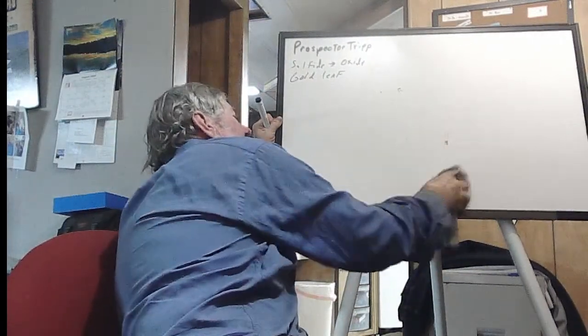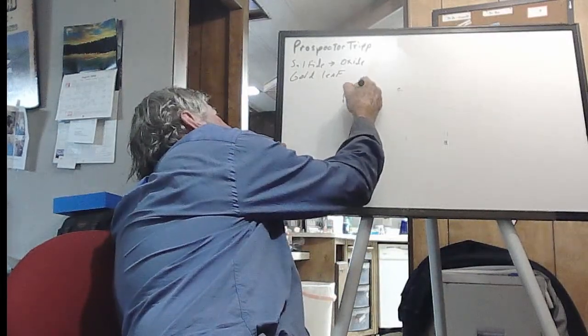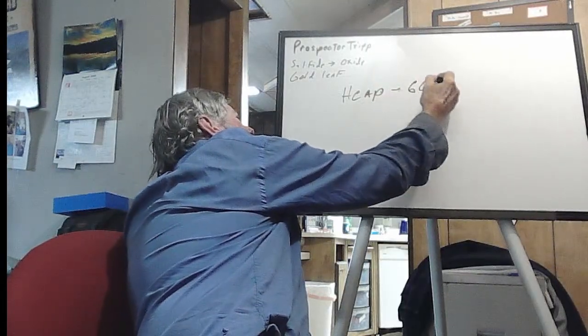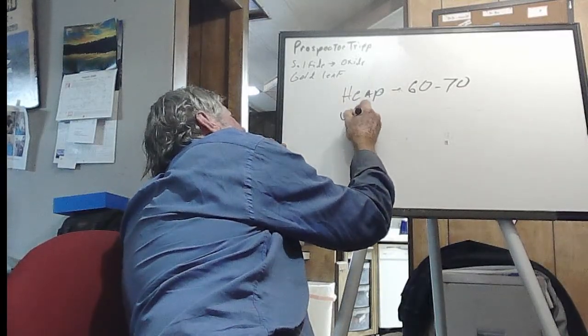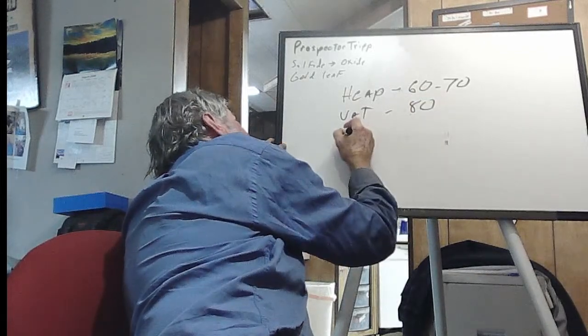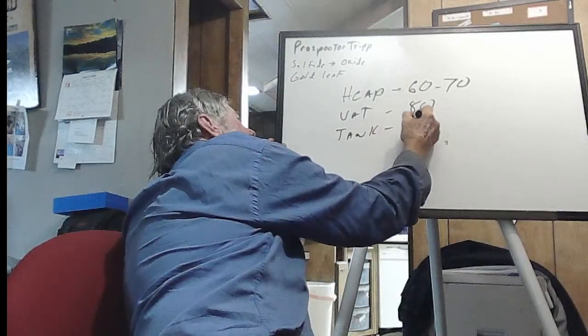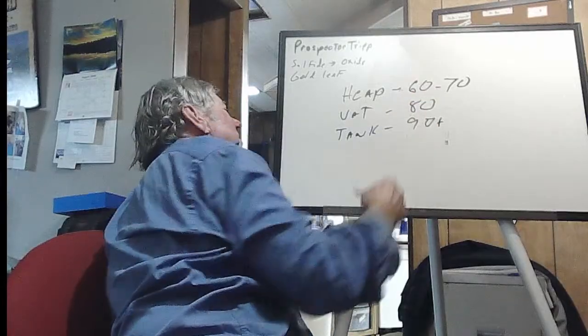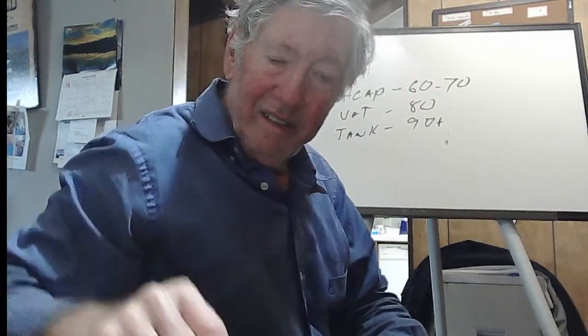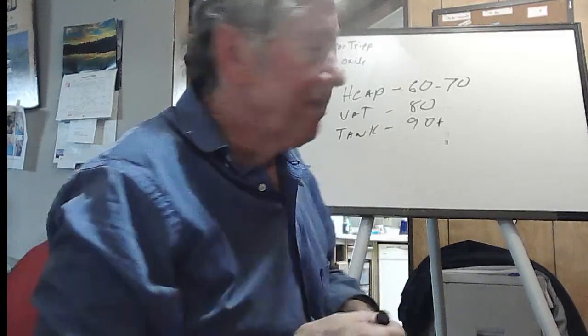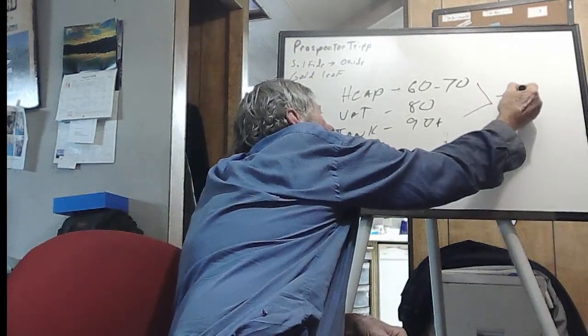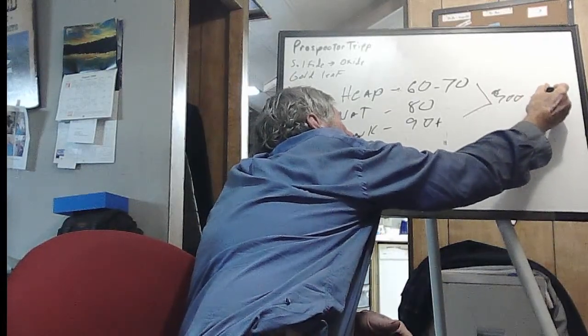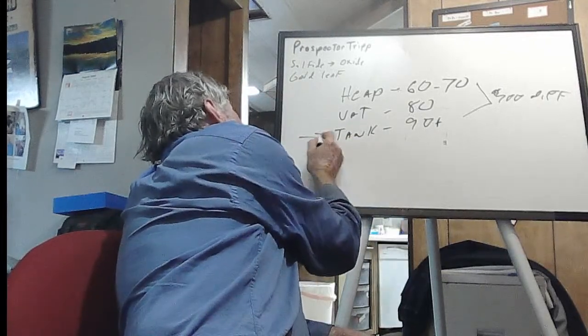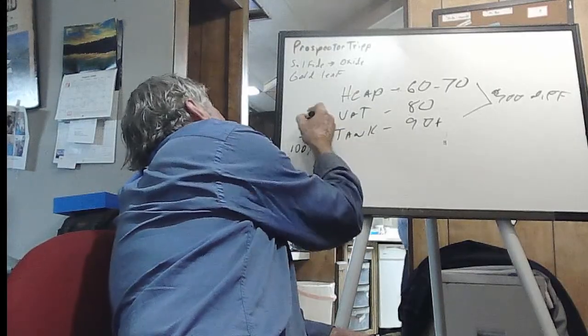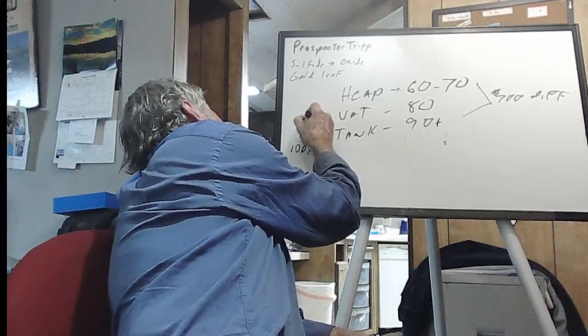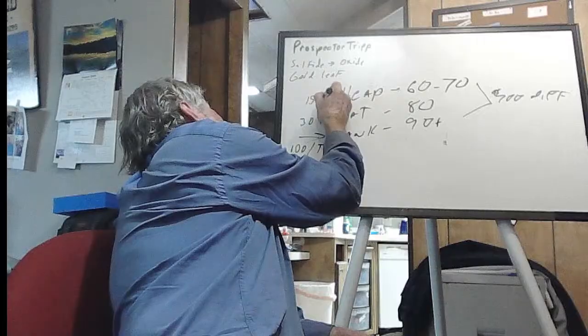For example, heap leaching might be 60 to 70%. Vat leach, call it 80%. Tank leach, agitated tank, 90+%. Okay, so 20% of 1 ounce to the ton would be $700. $700 difference. This cost might be $15 a ton. This would probably be more like $30 a ton. And this is more like $100 a ton. Okay.